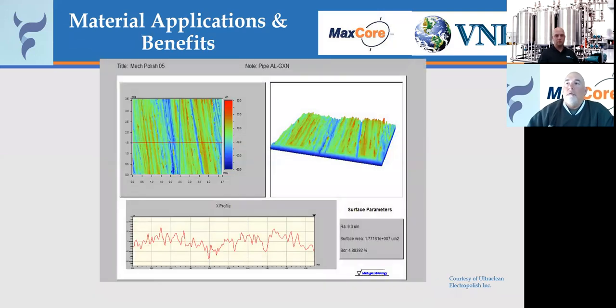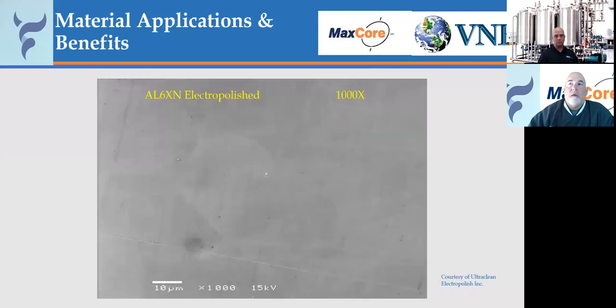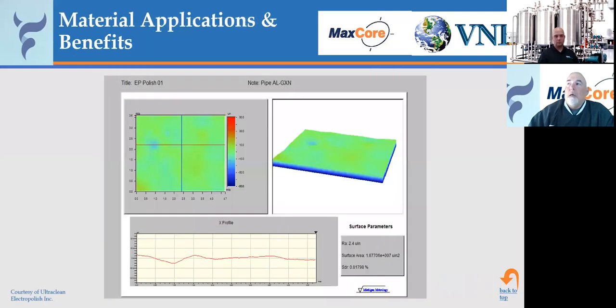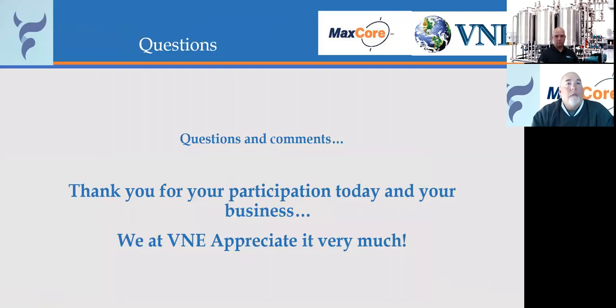And again, this is a mechanically polished AL6XN, the same type of thing you see. Then of course, after electropolishing, you get a nice smooth featureless surface. So you can get the same type of benefits for these higher alloys that you do with 316L stainless steel. They certainly can be electropolished to a satisfactory result. So with that, that's the end. I appreciate your attention and your participation.